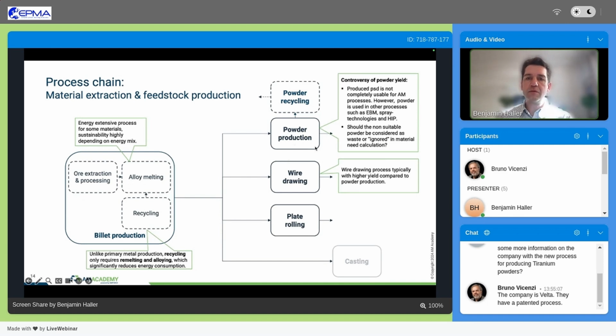Then when it comes to powder production, one important factor will always be the powder yield. And this is a big controversy in the industry. When we look at additive manufacturing, for example, laser powder bed fusion, what we use is typically a particle size from 20 to 60 microns. Depending on the powder production process, we have a yield factor in this powder range of around 40, 50%, which, depending on the technology, would already be very, very good. In some cases, it will be lower.